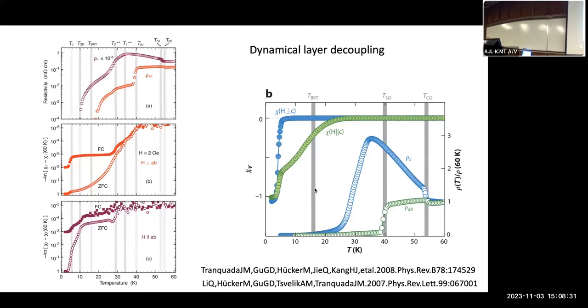here you can see things on a logarithmic scale. So first, this is zero field cooled. This is field cooled. This is for the magnetic field in the C direction. This is for the magnetic field in the AB plane. The scales are the same here, but this is logarithmic. So what you can see is that you do start seeing some diamagnetism here, right? You don't get full Meissner screening until you go below 4 Kelvin.